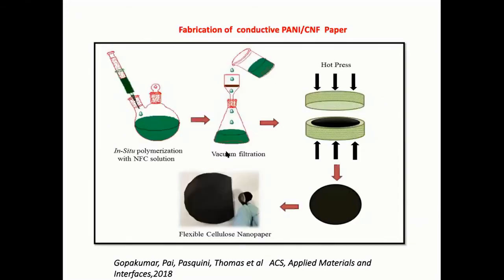My PhD student has taken nanocellulose dispersion made from banana stem, injected aniline, and went for the polymerization process. We did a vacuum filtration process and hot pressing using a compression molding press. You know what we made? We made conductive paper. Very thin conductive paper we have made. Very, very flexible, thin conductive paper.